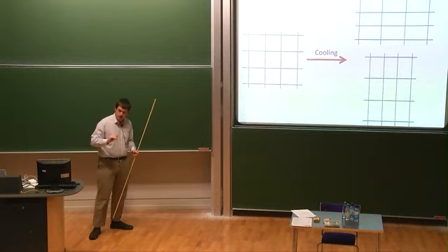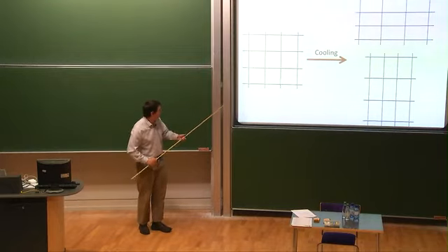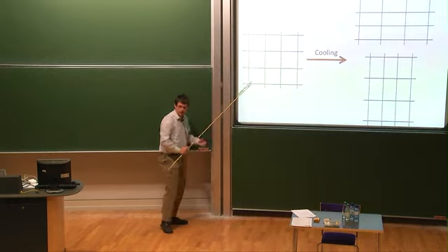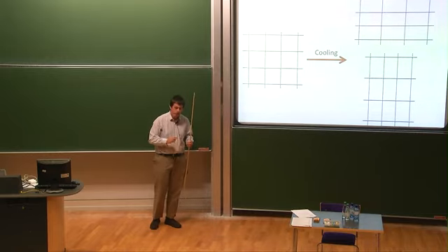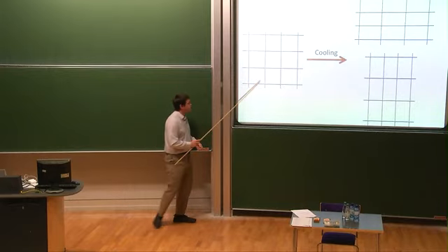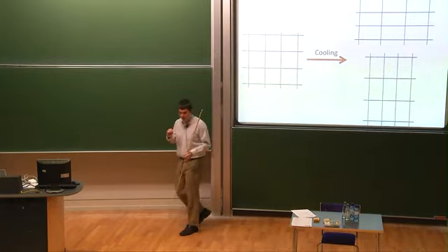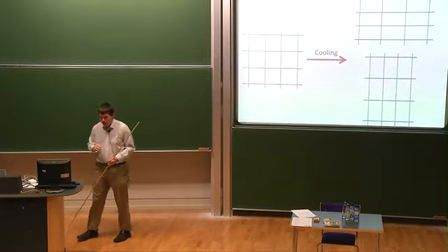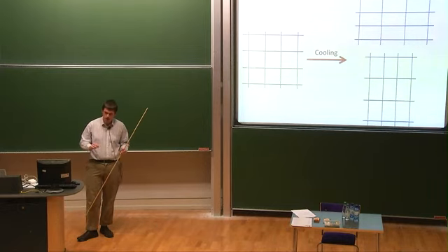Symmetric A to symmetric C, you really can do this, because you can imagine a symmetric A polydomain, which is like the high symmetry polydomain, right? It's the high symmetry state because I'm going to move to symmetric C, but it's polydomain because it can point in all sorts of different directions, even in the liquid. And then I cool to symmetric C, and I break the symmetry at each point, and then you get something that really is mathematically analogous to a polycrystal in the martensite literature. And whether that's going to be hard or soft, that's the one I really don't know, actually.